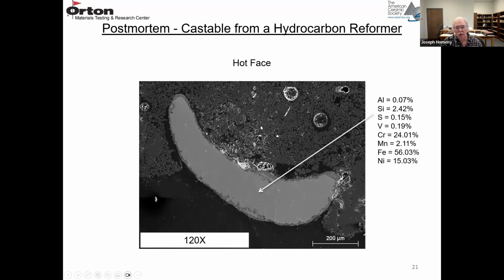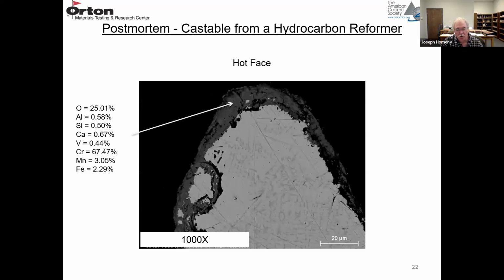And also in this particular refractory, there's some metal fibers. And this is a cross-section of one of the metal fibers. It's a stainless steel fiber. So it contains Cr, chrome, iron, and nickel. So about 24% Cr, 56% Fe, and 15% nickel. So that's a stainless steel fiber. I thought I'd just show you what happens to these fibers in service.